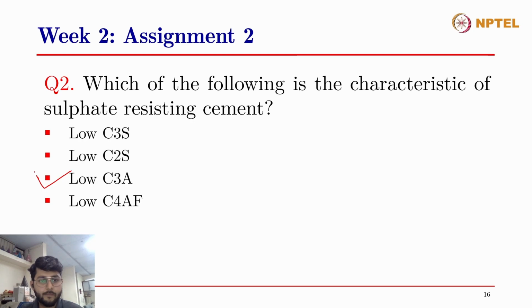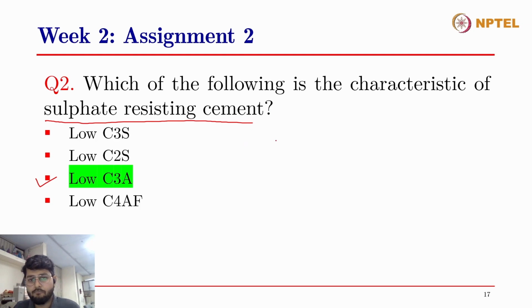Excess of C3A will react with the sulfate and form ettringite, which is expansive and can cause cracks. Right, that's the correct answer. Thank you. Yes, so the correct answer to this question is low C3A content is required in sulfate resisting cement.